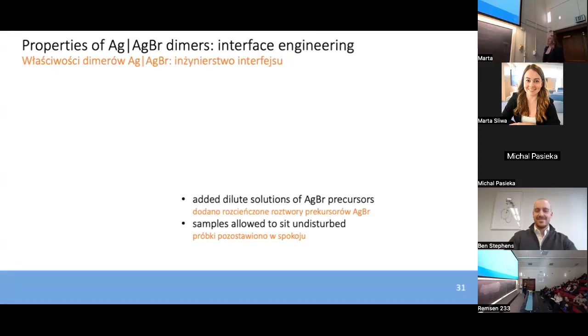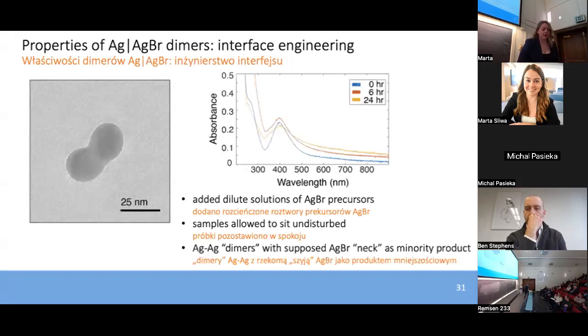So we thought that we could potentially grow silver bromide on the 111 facet of this silver nanoparticle, perhaps control for its size, shape, and thickness to be a little bit different than that nice round silver bromide that we previously had, and in that way access some different modal profiles. So it turns out that when we add these precursors or those dilute solutions of silver bromide precursors, let the sample sit undisturbed, we get some silver-silver dimers. So in this case, it's not silver and silver bromide, but two silver nanoparticles that are joined by what we think is a silver bromide neck material here. Now these particles make up less than 30% of that final sample solution.